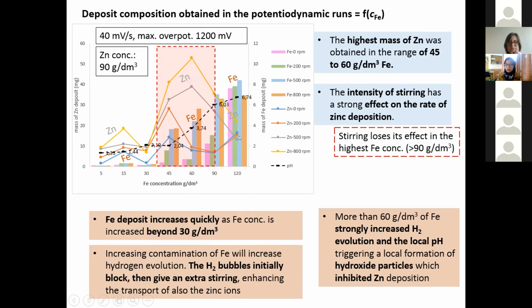Here, the bar is for the iron and the line is for the zinc. We can see that if we don't separate the zinc and iron, even with a small amount of iron, we still see that iron will contaminate our result. And as this increases, more iron is deposited. But what is interesting here is that at iron compositions of 45 to 60, it promotes more zinc deposition while more iron is inside the solution.